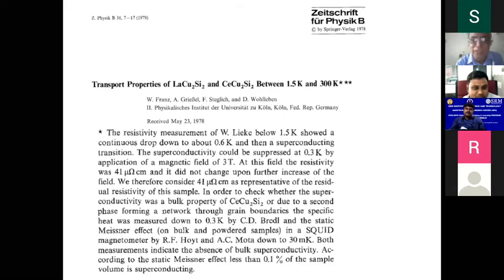Okay, this particular paper was in a very prestigious journal in those days for Germans, and these authors found another interesting feature. Cerium copper two silicon two had a large effective mass and a low-temperature heat capacity, and it doesn't order magnetically, though it is supposed to. Despite that, they prepared some 30-40 materials, and a few exhibited superconductivity. That was again surprising, because you expect cerium, historically, there is another two hours of talk on that. When you have a huge magnetic moment, you are not supposed to get superconductivity. Magnetism and superconductivity are supposed to be antagonistic, at least in those days.